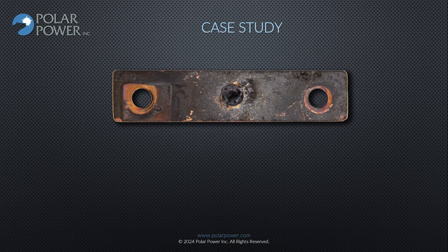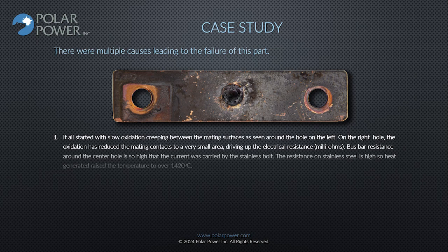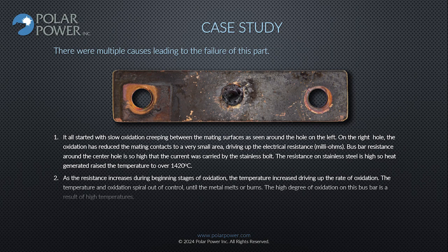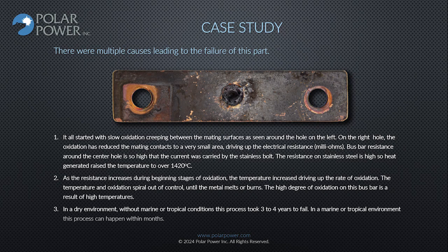There were multiple causes leading to the failure of this part. It all started with slow oxidation, creeping between the mating surfaces, as seen around the hole on the left. On the right hole, the oxidation has reduced the mating contacts to a very small area, driving up the electrical resistance to milliohms. Bus bar resistance around the center hole is so high that the current was carried by the stainless bolt. The resistance of stainless steel is high, so heat generated raised the temperature to over 1420 degrees Celsius.